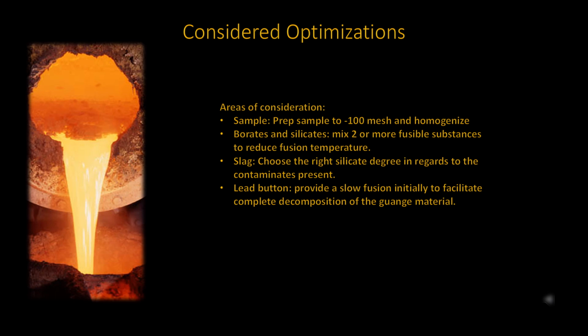To lower the fusion temperature of the charge, 2 or more fusible substances are used. In most cases, that would be the borax and silica. In order to create the almost perfect slag, a ratio between the borate silicate slag and a base is used. Sodium carbonate, commonly referred to as soda ash, is used as the base material, which also aids in reducing the fusion temperature. The slag, as already discussed, must be at the right viscosity, and a low fusion temperature is applied during the initial stages so that the decomposition of the material starts early.